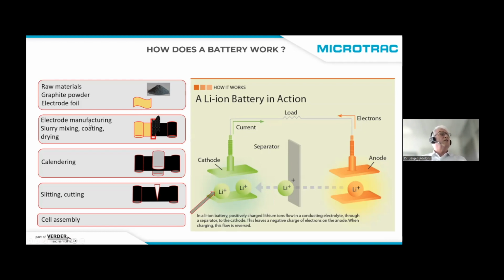So we do the electrode manufacturing. That means we have the copper foil. For example, we have a slurry. We coat this slurry, then we apply pressure and heat in the calendering process. And finally, it's cut and slit, and then we do the cell assembly.